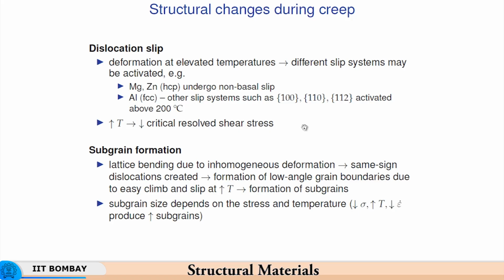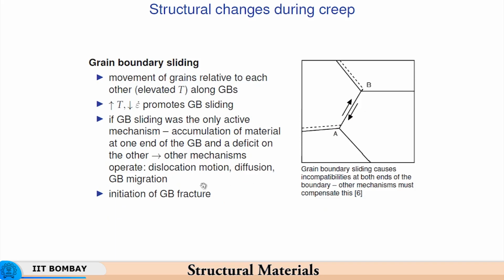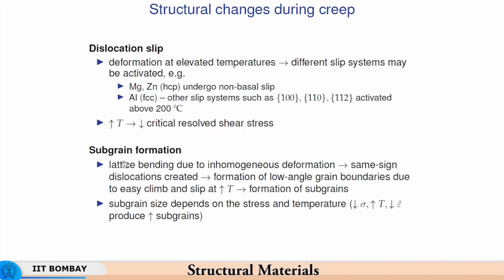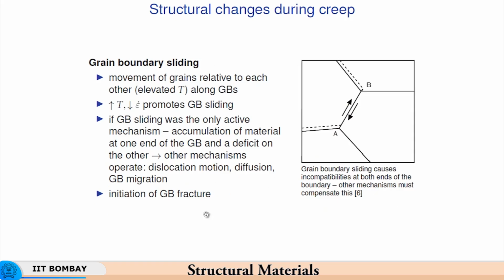That is one aspect. Second aspect is subgrain formation, and so we need to understand that formation of low angle boundaries due to easy climb and slip at increasing temperature leads to formation of subgrains. So, these are some of the structural changes during creep, due to which the creep becomes feasible, the deformation under high temperature becomes feasible. Add to that, you have grain boundary sliding taking place as the